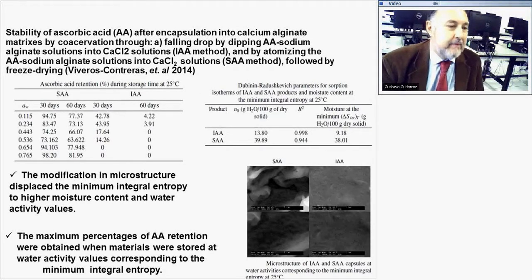Rubinos did the study on the stability of ascorbic acid after encapsulation in calcium matrices by dipping sodium alginate solutions into CaCl2 solutions. This is the paper. Atomizing the sodium alginate solutions into CaCl2 solutions, that was the method, followed by drying.